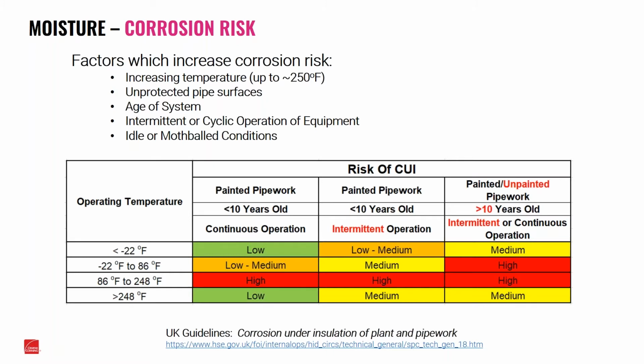You see that if we're operating our equipment continuously, pretty much outside of that high risk zone, so that's going to be 86 degrees and below or 248 degrees and above, there's really a much lowered risk of corrosion underneath insulation. However, if you look at that 86 to 248 degree range, that's the range where you have enough heat to actually keep that water warm, where you're kind of driving that reaction rate that we talked about, but not enough to fully evaporate that water off of the system. So you basically have a hot, wet condition, and that, of course, is going to facilitate any kind of corrosion activity that you have going on there.